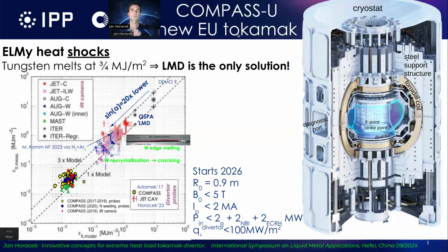COMPASS Upgrade is a new tokamak in Europe, which we are now building in Prague, Czech Republic. And it's based on a very strong magnetic field. It will be up to 5 Tesla thanks to copper-cooled coils. And it will reach up to 2 megaamperes, even though it's a relatively small, medium-sized tokamak. The power will be, however, very high. And in attached divertor, we can reach up to 100 megawatt per square meter according to our scalings. So this would be a very good way to test these innovative new techniques.